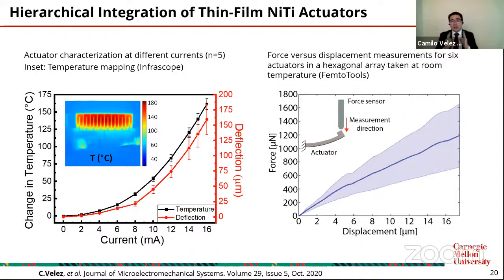If you change the composition, and this is for 50-50 nickel titanium, you can shift the hysteresis curve to lower temperatures. We haven't demonstrated how low we can go in that direction, but it can be tunable by a certain amount. I won't promise that at freezing temperatures it's going to work. I'm not so sure. I will need to work on that one.